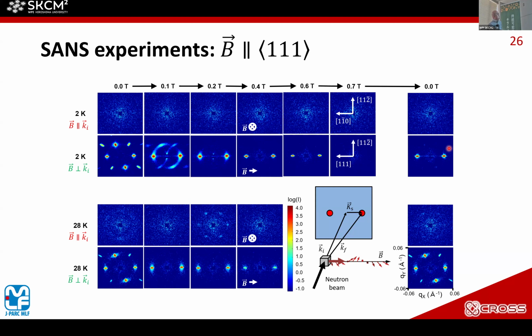As you can see, there are many Bragg spots at zero applied field because the manganese silicide has a cubic crystal structure. So the equivalent chiral axes, there are 4 equivalent chiral axes. So the conical phase from the one chiral axis and also from the other chiral axes are observed. And these two small peaks are multiple scattering.